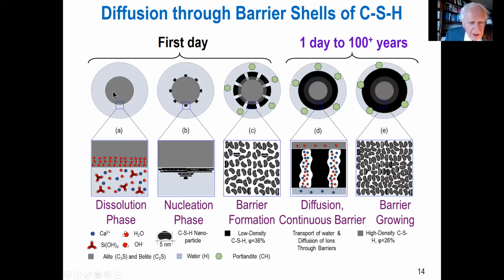So what we have the first day, we start with a cement grain, alite, C3S, with water around. It starts rapidly hydrating, and within 4 hours there is a set. These layers contact each other, so this grows. And from 1 day on, we have the anhydrous grain, not yet reactive, enveloped by a shell of CSH, calcium silicate hydrate. And that shell is slowly growing. You see it here indicated by the particles, it densifies.